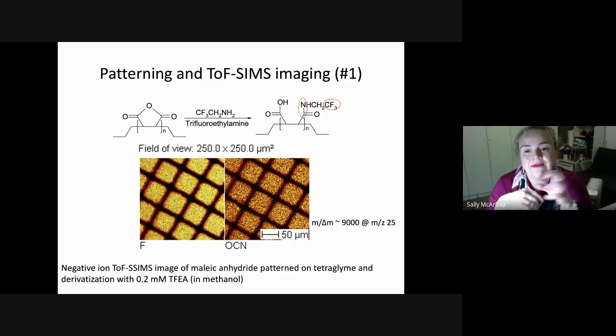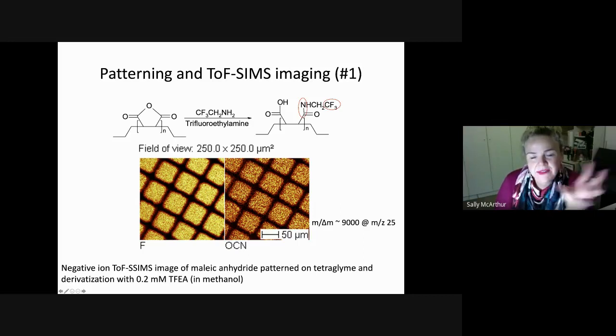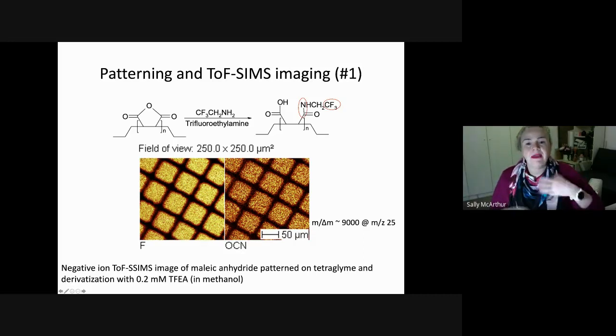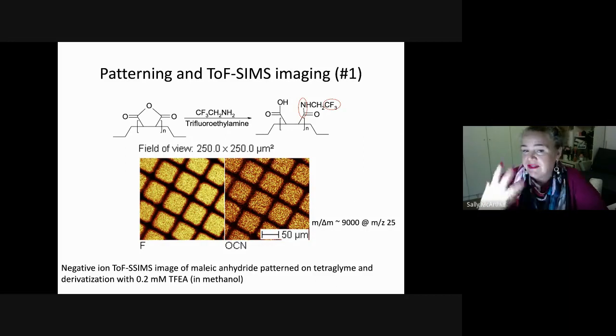anhydride group is still reactive on that surface in those brightly lit areas, because the fluorine areas are bright here. And the nitrogen-containing species, this is negative ion TOF-SIMS imaging, and the nitrogen-containing species also correlate with the fluorine, so that gives us another way of looking at this. The pieces in between aren't patterned and aren't picking it up, indicating that the glyme surface is not reactive to it as well. So we haven't damaged the glyme surface, that's our assumption from here, but actually we've got positive ion TOF-SIMS images that show us clearly that the tetraglyme is still there.